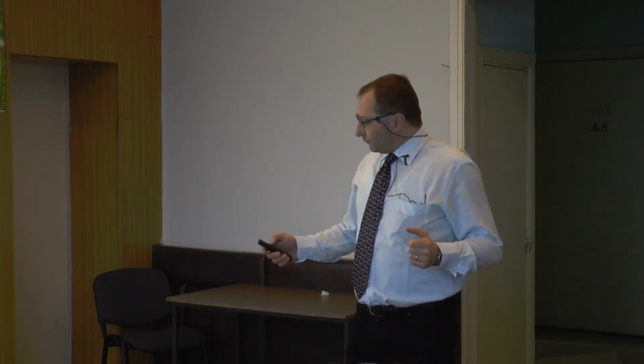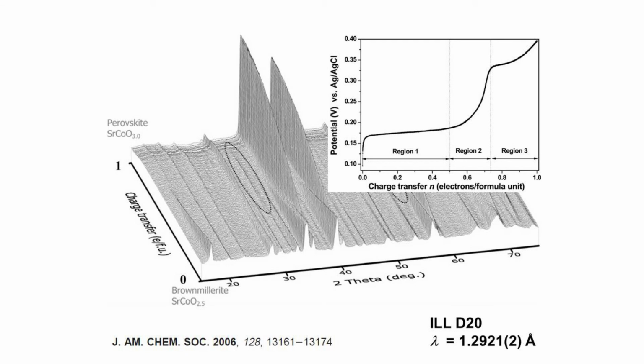So this has been done in situ at the neutron source at ILL, D20 diffractometer. This is a 2-day experiment, and we have imagined that we have an electrochemical cell, and we run the diffraction in situ. You can see clearly that the peaks of the brownmillerite phase progressively go down, while the peaks of the cubic phase start up. In a given region, we see some superstructure peaks as well that somehow we have to understand.